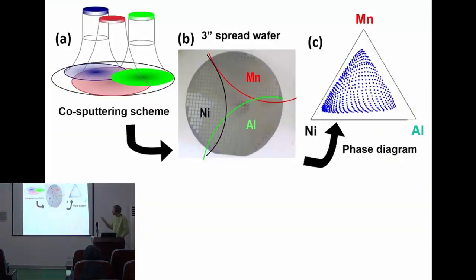We know several similar things also in material science. I have taken here a randomly chosen example from the recent literature, where people study different alloys of nickel, aluminum, and manganese made by sputtering these three elements on one wafer. And you have chosen the focus of the three beams in such a way that you have a varying gradient of nickel, aluminum, and manganese concentrations across the wafer. So by one sample production step, you have these different points in the ternary phase diagram of these three elements. And if you then have an X-ray diffraction machine that can make very focused experiments, you can then scan all these dots on your wafer to find, for instance, the crystal structure and the lattice parameters of all these different phases in the phase diagram.